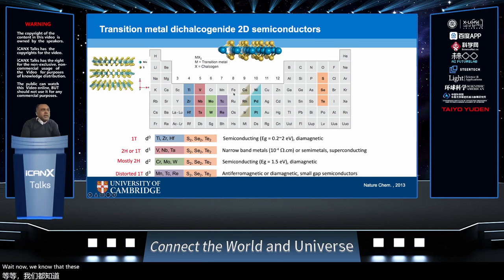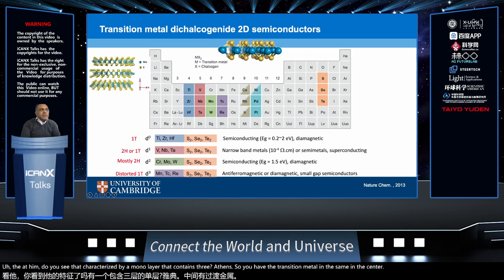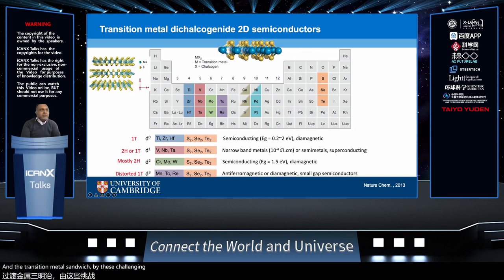Now we know that these transition metal dichalcogenides in this chemical formula form these layered compounds, right? These layered compounds are similar to graphite in the sense that they're characterized by strong in-plane bonding while weak out-of-plane bonding. This allows us to then isolate individual layers of these TMDCs, and therefore we go from a bulk layered material to a 2D material. In contrast to graphene, which is pure carbon, the TMDCs are characterized by a monolayer that contains three atoms. So you have the transition metal in the center, and the transition metal is sandwiched by these chalcogen atoms.